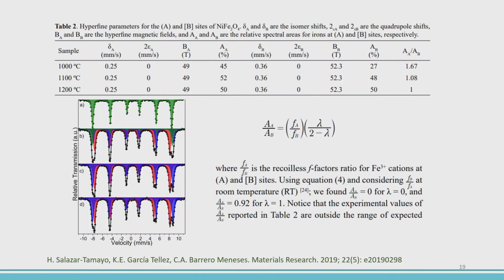And the other explanation is that because the area is proportional to the number of iron atoms, we can guess that the irons at the B sites become populated, meaning the vacancies are occupied as temperature increases, and this is nicely in agreement with the X-ray diffraction.